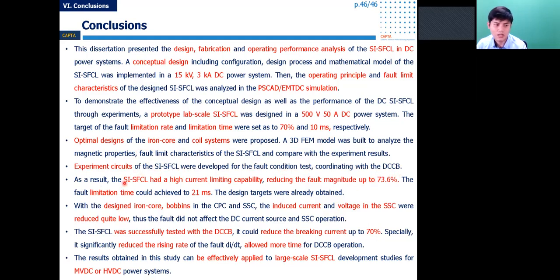As a result, the SI SFCL had a high current limiting capability, reducing the fault magnitude up to 73.6%, and the fault limitation time could achieve 21 milliseconds. So the design targets were already obtained. With the design of iron core pop pins in the primary and secondary coil, the induced current and voltage in the secondary coil were reduced quite low. So the fault current did not affect the DC current source and secondary coil operation. The SI SFCL was successfully tested with the circuit breaker.